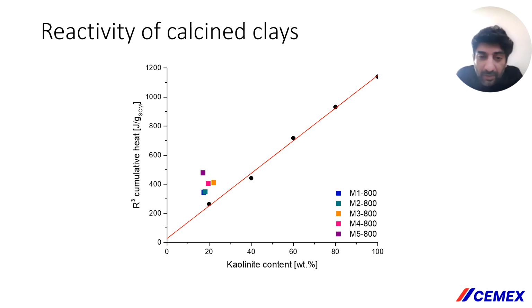So the figure shows the reactivity potential of M1800 and M2800 is equivalent to a kaolinite content of about 30%. M3800 and M4800 show a slightly higher reactivity potential equivalent to 35% kaolinite, whereas M5800 was equivalent to about 40% kaolinite. However, it must be noted that the maximum kaolinite content for all the raw clays was less than 23%. So accordingly, these findings are very significant given that the reactivity of clays comprising circa 35 to 40% kaolinite are considered ideal for LC3 systems.